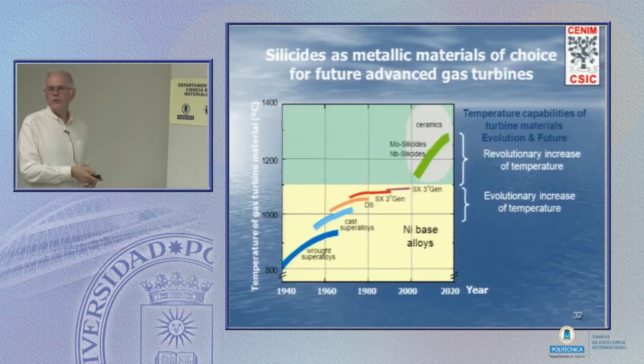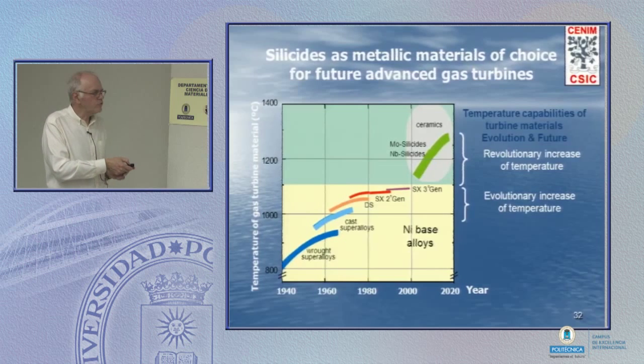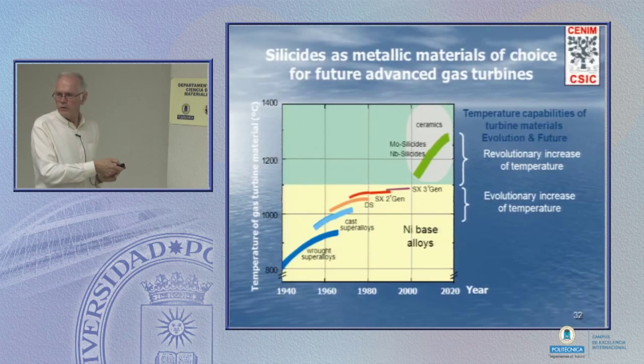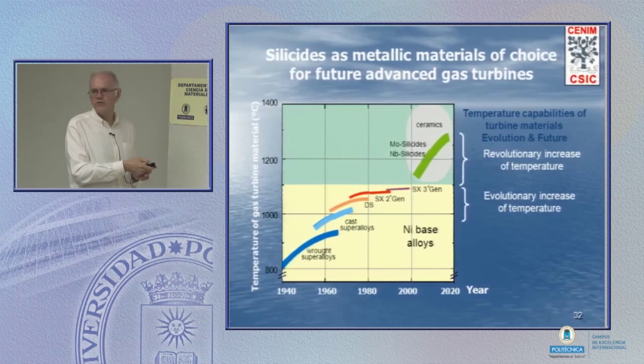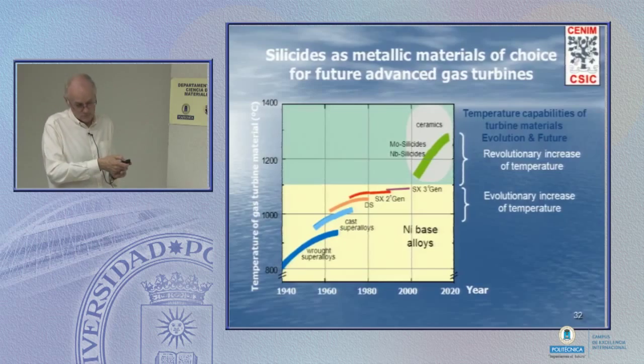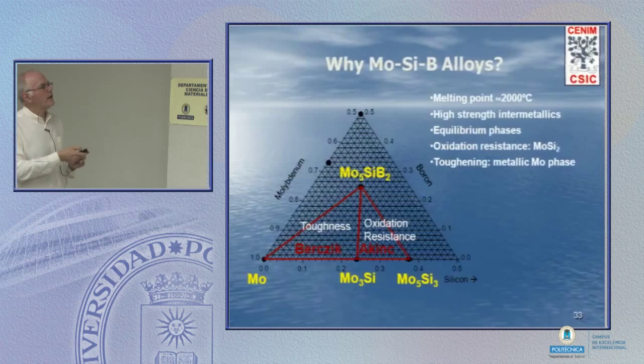So again, you also know this story, the upper temperature limit of usage of superalloys over the decades: evolution of composition, evolution of processing, cast, wrought, directionally solidified, single crystals. But what is clear is that superalloys are not going to go very much more in terms of gain of temperature, whereas just around the corner, we're almost there, supposedly, are these silicides. So why the moly-silicide-boron specifically?